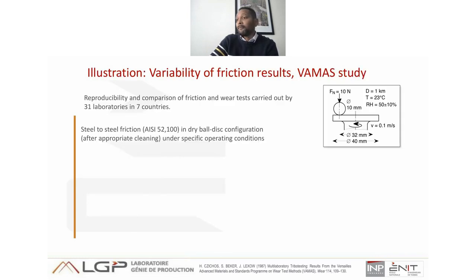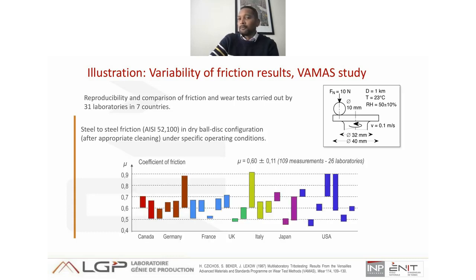The example of the VAMAS study illustrates this systemic view. In this study, which involved 31 laboratories from 7 different countries, tribological tests with identical operating conditions were performed. This involved rubbing steel balls against steel planes with the operating conditions noted on the top right of the slide. The results give very spread information, very spread friction coefficients. And the compilation of these results makes appear a huge difference between these laboratories.